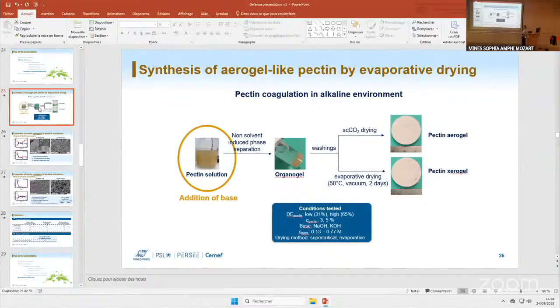Especially, in fact, there is a trick for progressive calcium release into the medium. You're right that the gelling is very fast, so it can bring some difficulties of homogeneity when you want to have a bulk gel. There is some trick. We try to avoid adding more parameters in the system, because non-solvent concentration and pH were already parameters. We try to avoid having calcium content in addition, because our main goal was to modify, to prevent aging. So when you find the suitable modification, then you can adopt the way to make the pectin gel.